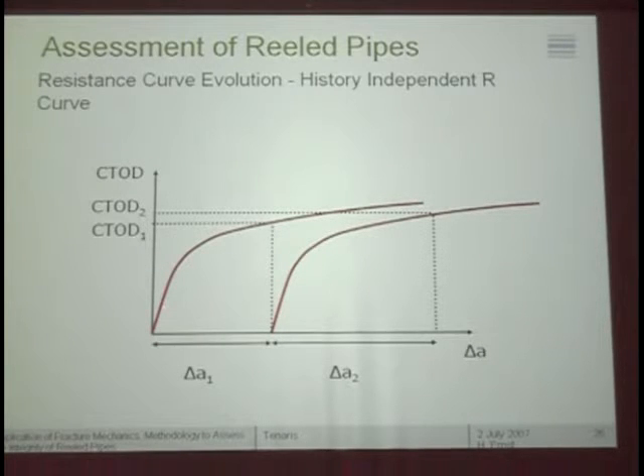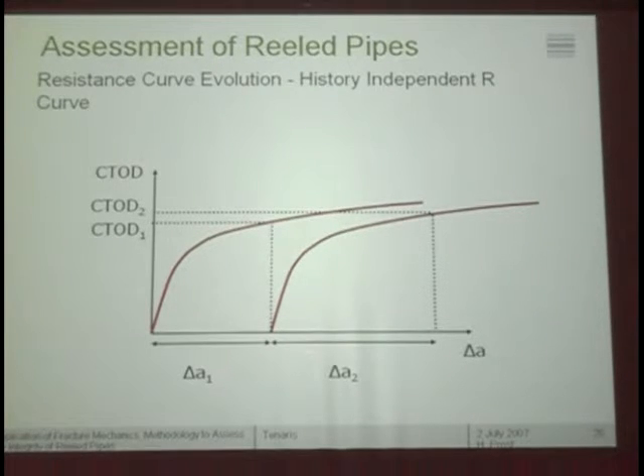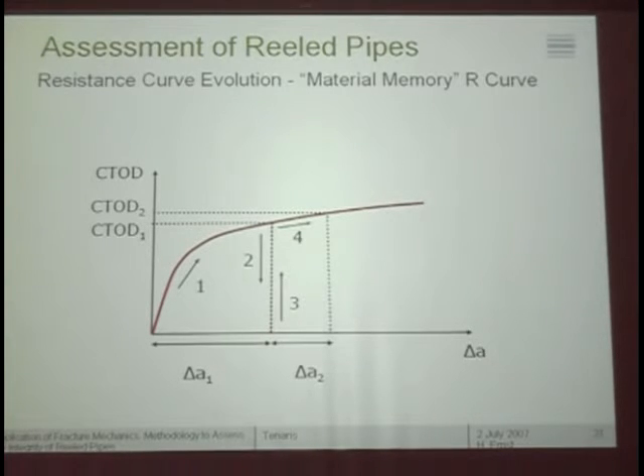This is the first of the two cases, the history-independent curve. You have the applied CTOD, this is the resistance curve. From there you can read off how much delta A1 you have for the first cycle. You unload, you come up again. If you go to a CTOD 2, you will have this much of crack extension. So you are adding crack extensions as if you didn't have anything before.